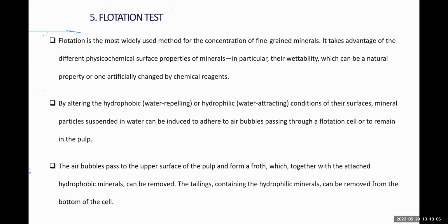Like for lead and zinc, if you are processing lead and zinc, once you get to the slurry, you have to add different chemicals. You have to add your MIBC, your xanthate, you have to depress, you have to activate with copper sulfate, zinc sulfate, and so on, because you want to play with your surface chemistry. You want to see which one can float at the expense of the other. So the surface chemistry property sometimes might not be an inherent nature of the material. Sometimes you have to enforce it by using some chemical reagents.